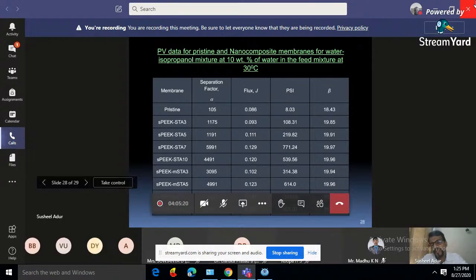Why does it happen? What happened here? STA 10, because the increased content of STA blocked SPEEK voids. That was the problem. So as I went from 7 to 10, at 10 weight percent composition of STA in SPEEK, it blocked SPEEK completely. Therefore, many of the voids got stuck with STA itself. Therefore, what happened? The separation factor decreased for 10. Similarly, if we see MSTA 3, 5, 7, 10, here also we can see that MSTA 7 is giving optimum separation factor and flux compared to 10. Once again, the same problem.